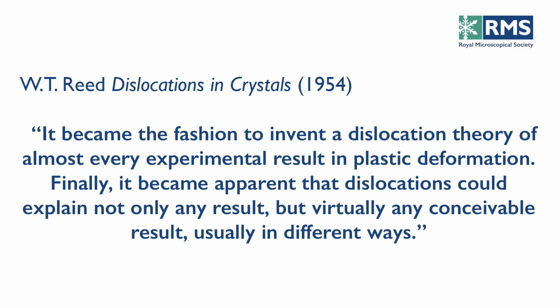And it was perfectly obvious that what was needed was an experimental technique. There is, in fact, a rather famous quotation by W.T. Read, who wrote a book called Dislocations in Crystals, published in 1954, in which he says it became the fashion to invent a dislocation theory for almost every experimental result in plastic deformation, and it became apparent that dislocations could explain not only any result, but virtually any conceivable result, usually in different ways. So what was needed was an experimental technique.